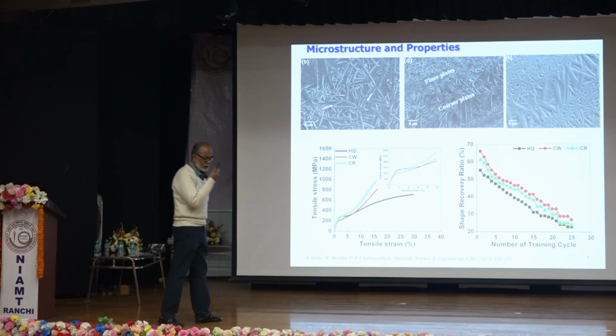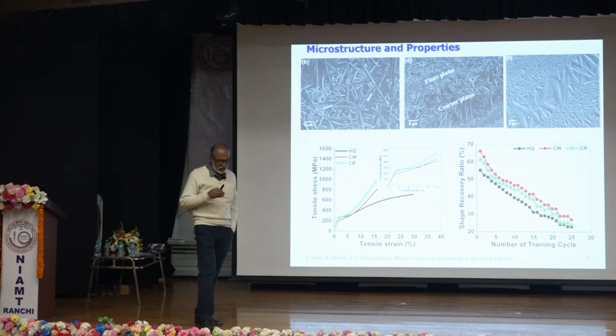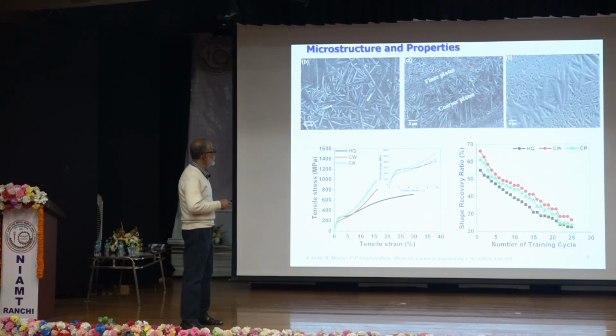Actually, during deformation, nucleation and propagation occurs in a certain localized manner, where there is strain in the favorable direction of strain. So it is not homogeneous and uniform. So we obtain banded structure. And when we deformed in, there is no significant difference in size and distribution of martensite. But in case of cryo-rolled sample, we found the bands with very fine martensite and coarser martensite. And we found there is adiabatic heating.